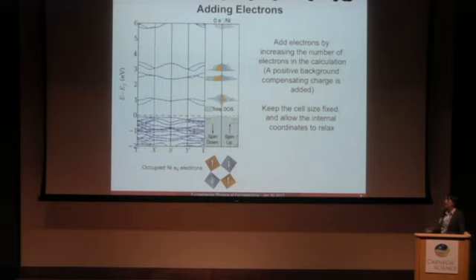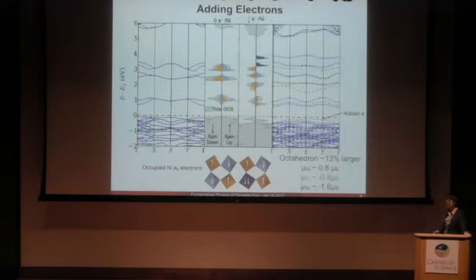So as we add electrons, I'm first just going to add an electron with a positive background. This can be done in VASP just by increasing the number of electrons in the calculation. When this happens, we see a marked shift in the density of states, and the number of bands themselves are now different in this region right above the Fermi energy. So what's happening is this nickel now has an extra localized electron. This octahedron is about 13% larger, and we see the magnetic moment doubles.